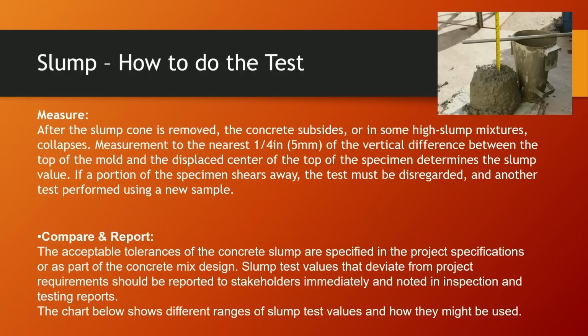So when you do the measurement, you put the rod on top of the cone, and then you put the tape on top of the concrete up to the rod. After the slump cone is removed, the concrete subsides, or in some high slump mixtures collapses. Measure to the nearest quarter inch the vertical difference between the top of the mold and the displaced center on the top of the specimen to determine the slump value. If a portion of the specimen shears away, the test must be disregarded and another test performed using a new sample. I actually had one shear away when I took the test. I had to do it again.